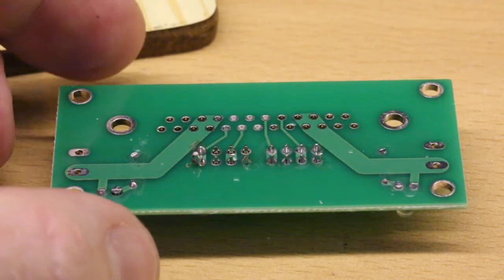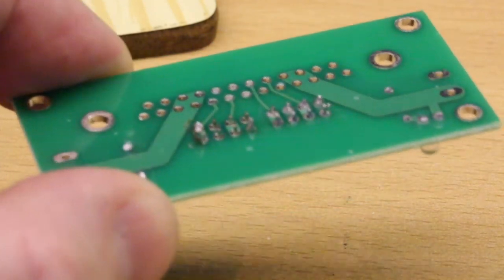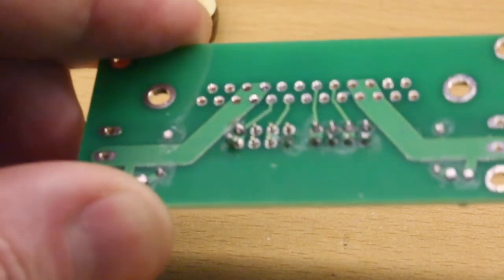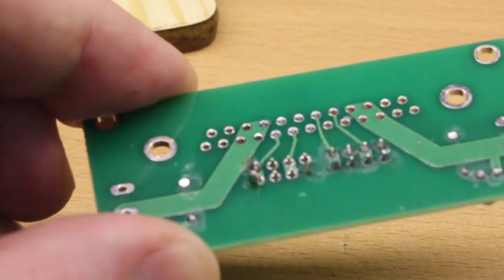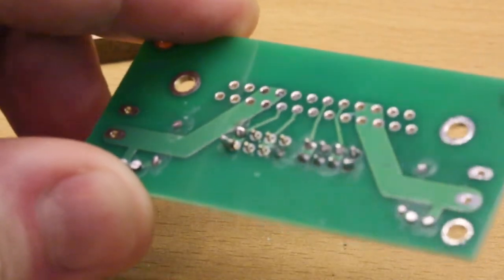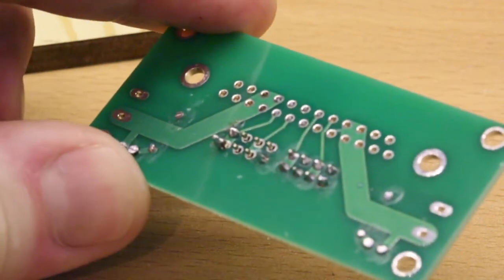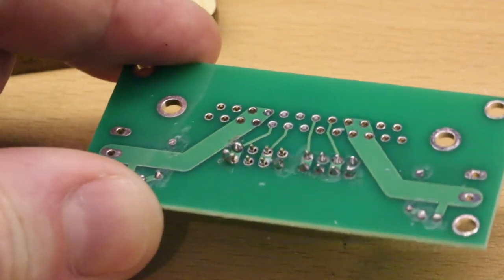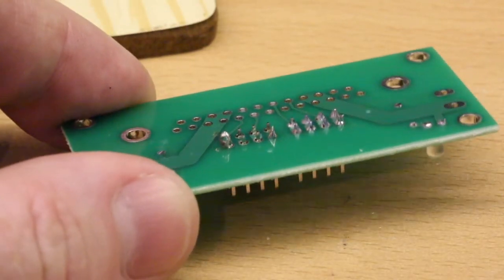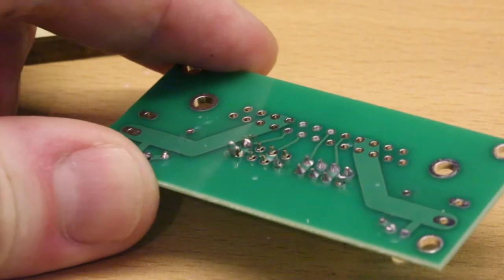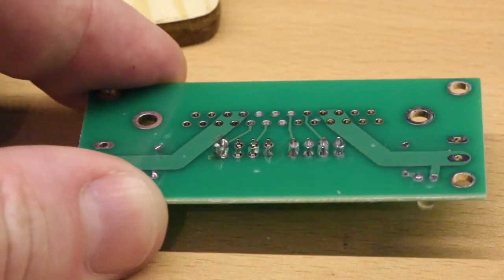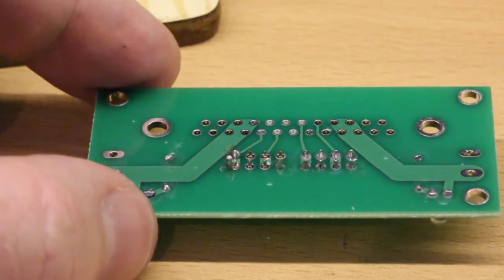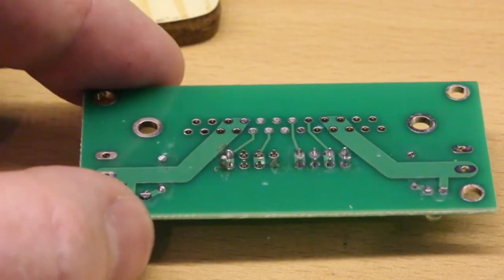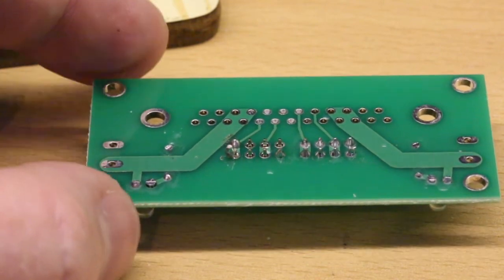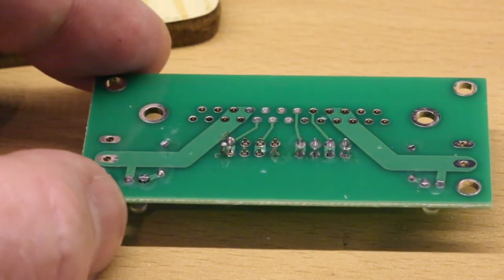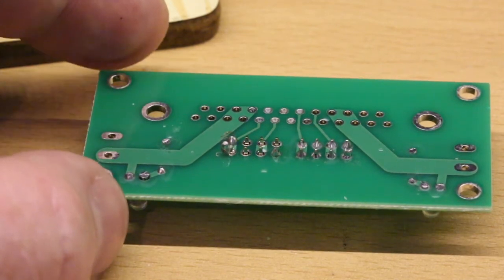Right, I've switched to a macro lens to show you a dry joint, but it's a bit tricky to show. But if you can see this component down here in the corner, this solder joint is not great. It's got way too much solder on it, and the solder doesn't actually go all the way around. That's typical of, if you ever open anything that you've bought cheap, like a cheap radio off the market, you'll probably find that a lot of the components will look like this, and it might just about barely be working. With a dry joint, what happens is you get solder between the two components, and it might make a mechanical joint for you, which means it'll stop the components falling out and moving around, but it won't make a good electrical joint.